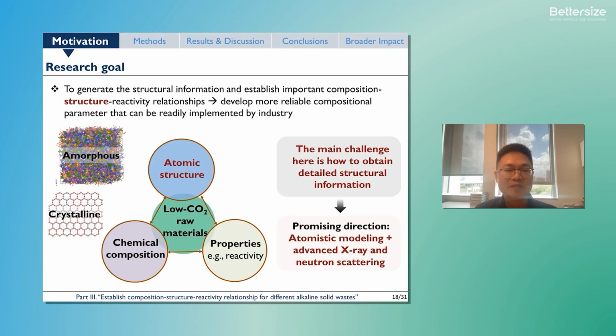But for amorphous materials, in the case of these waste materials, their structure cannot be determined using conventional X-ray diffraction experiments. But for this purpose, atomistic simulation combined with advanced X-ray and neutron scattering is a promising solution, which is what I'm going to show you today.